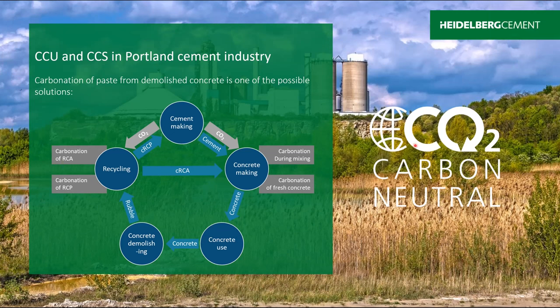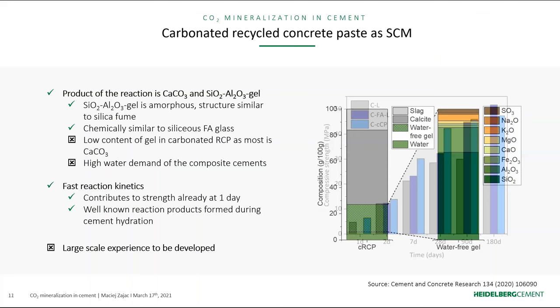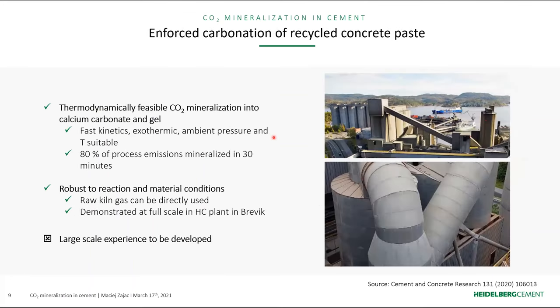My question is, if you've separated out the cementitious part of the concrete, why not just feed that straight back as feedstock to the cement plant? That would give you, in my opinion, a double win. One being that you wouldn't have to calcine limestone because you're bringing in the lime. But the second one would be that you could reduce your fuel consumption, because the calcination of the limestone is the main heat absorbing factor, so you could greatly reduce your heat consumption. You would have less CO2 because you'd have less combustion and you wouldn't calcine the lime, and you could skip that step of carbonating the lime.